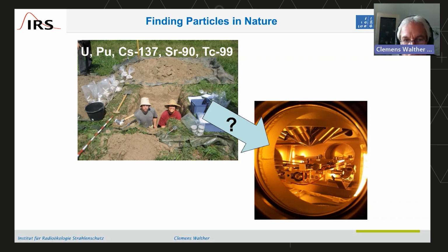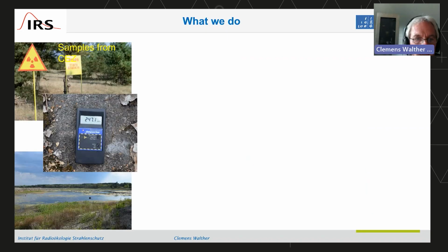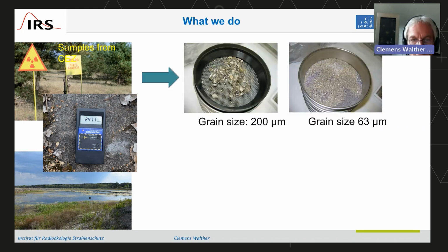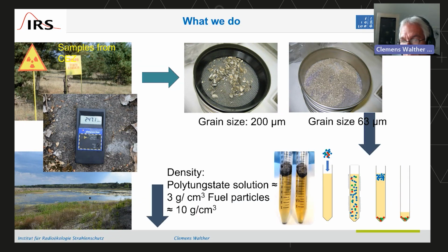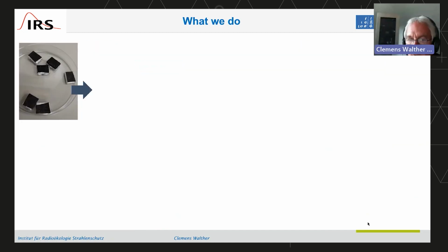Of course it's a bit more than this, because the left picture shows you how you get your samples in nature, and the right is the instrument you want to put it in. And it is not a good idea just to take a shovel of dirt and put it in there. That might not be what you want to measure. So what we really do is find some samples, and we go to regions where we expect radioactive samples to be. Then we do some sieving, have the grain size reduced step by step, and then we look at very heavy particles, because particles containing uranium have a high density. We do a special kind of flotation, but this is not water. This is polytungstate that has a specific density of 3 grams per cubic centimeter. So everything with a density lower than that, for instance aluminum phases and silicate phases, floats on top of that liquid, and we are only interested in what is even heavier and falls down.